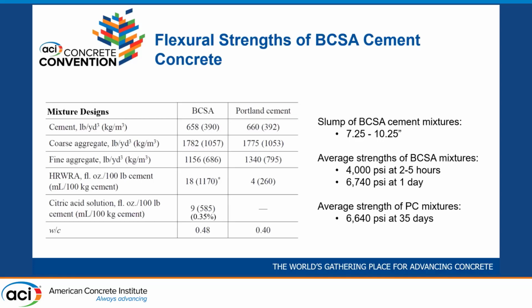So in terms of slump, the BCSA beams were between 7¼ and 10¼ inch slump. Our average strengths for the BCSA cement beams were 4,000 PSI at 2 to 5 hours and a little over 6,700 PSI at 1 day. And you can see that just about matches the strength of the Portland cement mixtures on the day that we tested them. So this was nice. We had a direct comparison between 2 mixtures that had similar strengths.